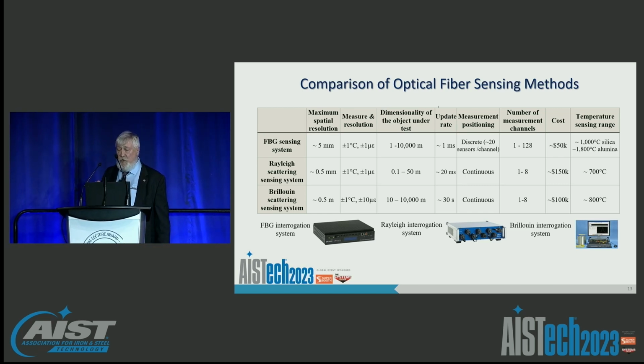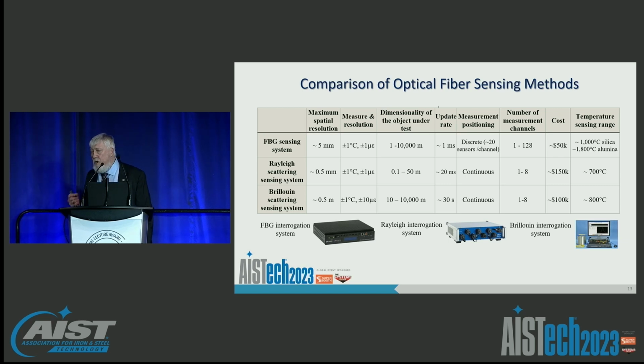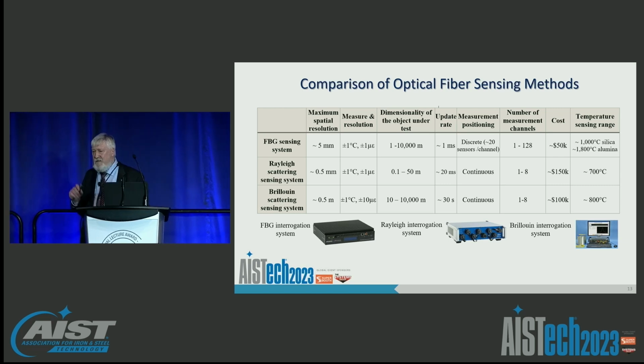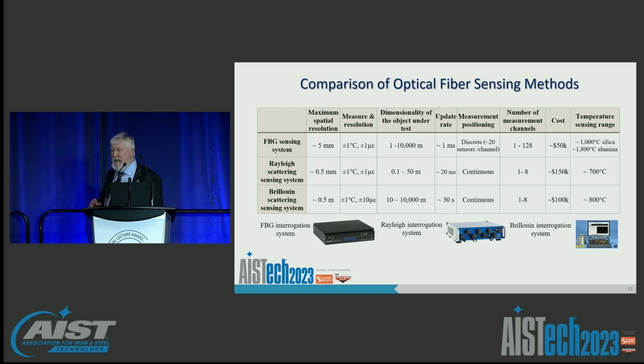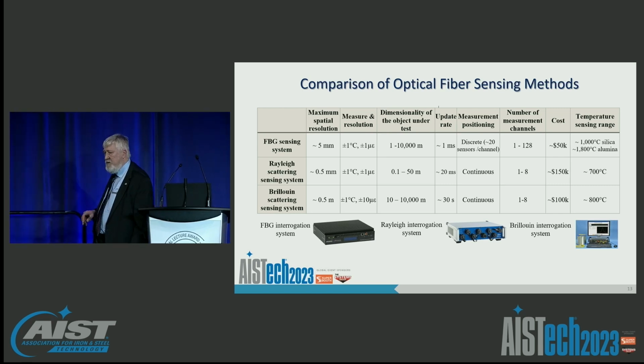So these multi-mode fibers typically are undoped. Oftentimes they're not cladded. The air around the environment is the cladding that contains the light, and that works for a lot of systems. In these systems, we can use undoped fibers, which can reach temperatures above 1000 C in applications. Whereas if we go to Rayleigh scattering, for example, we use a single mode fiber only. It can measure 0.5 millimeter resolution, and its temperature limitations are a little bit lower because of the dopant migration, about 700 C.